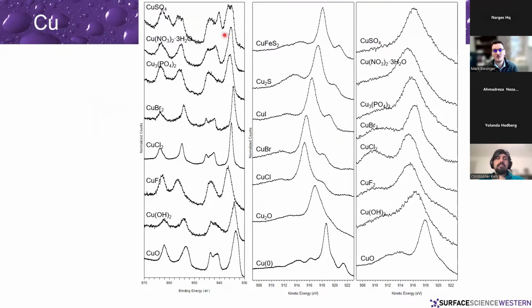For copper 2 species, we have that shake-up structure that I talked about earlier that means, okay, we've got copper 2. Copper 1 and copper metal don't show this structure. But you can look at that shake-up structure and see that it changes dramatically as we have different species present. So we actually use these spectra to do curve fitting procedures to say, okay, I've got so much in my copper 2 species, I'm seeing copper 2 chloride, I'm seeing copper 2 oxide, etc.